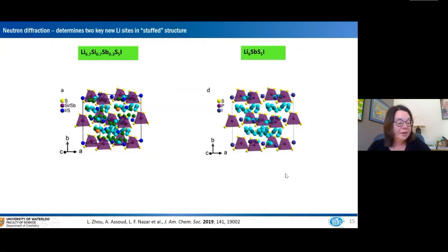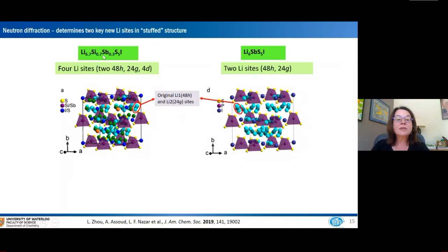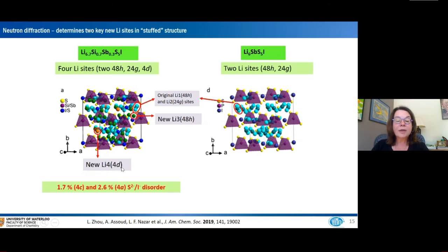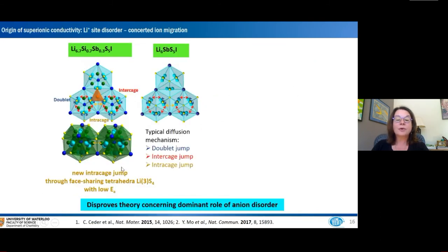And the reason for that is shown in this overhead, where effectively in the pure antimony iodide, we have 2 lithium sites, whereas in the silicon substituted material, we have 4 sites. We introduced 2 additional sites in the 48H and the so-called 4D site, and again, very little anion disorder.